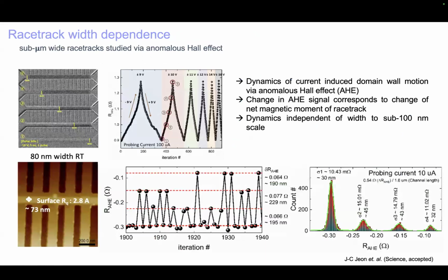And we can do this in racetracks that are down to 73 nanometers wide. So you can see here the motion of a single domain wall in a 73 nanometer wide racetrack. In the bottom left, you can see the platinum electrodes where we detect the Hall signal, and the wing where the platinum layer is slightly wider than the racetrack. And you can see here we're detecting the Hall signal at 4 positions where the domain wall is positioned along the racetrack with a sensitivity of a few tens of nanometers, and we can position one domain wall with respect to another one with a spacing of better than 100 nanometers. So all of this means that basically we built racetracks now at technologically relevant length scales and demonstrated that we can detect individual domain walls in these racetracks.